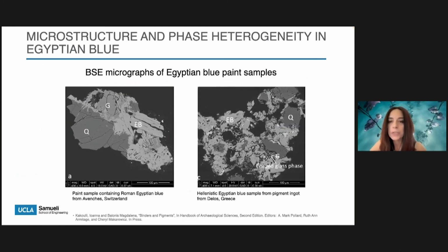Traditionally, scanning electron microscopy and microprobe analysis assisted in the classification of Egyptian blue pigment based principally on the characterization of the major phases. These two backscatter electron images of samples of Egyptian blue from Switzerland and Greece respectively show the major crystalline phases of Egyptian blue, unreacted quartz, and interstitial glass. What is different in these samples is the composition of the glass phase, which varies according to the fluxes used.